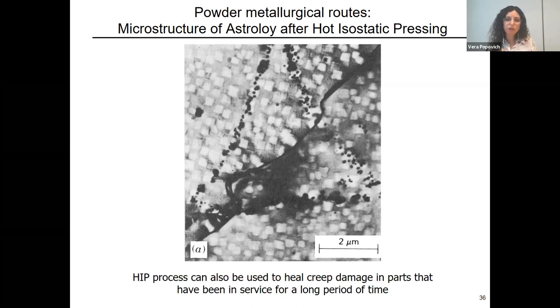This kind of technique, as I already mentioned, is very commonly used to heal creep damages. So for example, if there's a creep damage, it can be used to grind those parts and then heal it again, yeah? Or when there's a certain crack, to apply pressure to heal the crack, especially the creep crack.